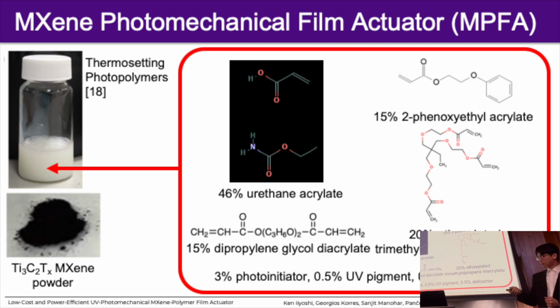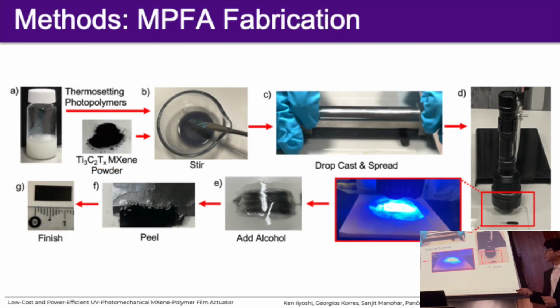So how we fabricated the film was to mix the Ti3C2 MXene powder, which is basically like this graphite-looking powder over here. We mix this with the thermosetting polymer by hand, and then drop cast this and spread it with a film applicator on Teflon or PTFE. And then we just do a quick photo curing in around 10 seconds, and then we peel it with the help of a little bit of alcohol. And we basically complete one film fabrication in around 10 or 15 minutes, which is pretty fast.